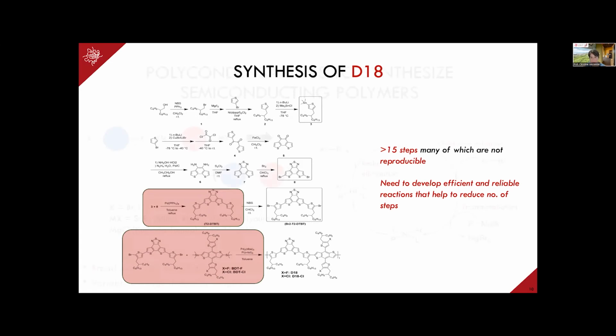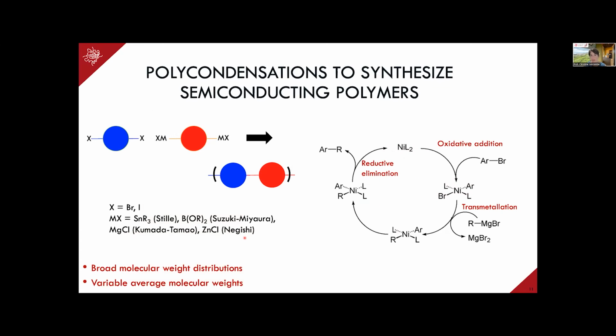So on that note, I just want to quickly introduce to you how we typically make semiconducting polymers. If you could imagine that these are aromatic rings that we're trying to connect together, the standard way that we make the polymers is we have one monomer, which would have two halogens attached to it. And then we have another monomer that has the organometallic species attached to it. And then we add in a catalyst, typically a nickel or palladium-based catalyst. This initiates the cross-coupling reaction, and you get this alternating structure forming. And many of you are probably familiar with this catalytic cycle of the repetitive cycle of oxidative addition, transmetallation, and reductive elimination, and so on.